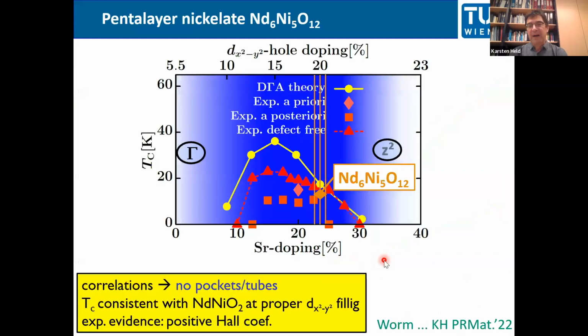Also, the 5-layer nickelate by Giulia Mundi nicely agrees with the overall picture here. There, interesting to see is that correlations in the 5-layer nickelates remove all pockets. And if you don't have pockets and you have 5 layers, you have a doping of 1/5 or 20%. So we are here, but since you have 5 layers and 3 inequivalent layers with slightly different doping, we have this kind of uncertainty in the doping range where this 5-layer compound is. But it also agrees, and it now has a positive Hall coefficient, and all this picture makes sense.